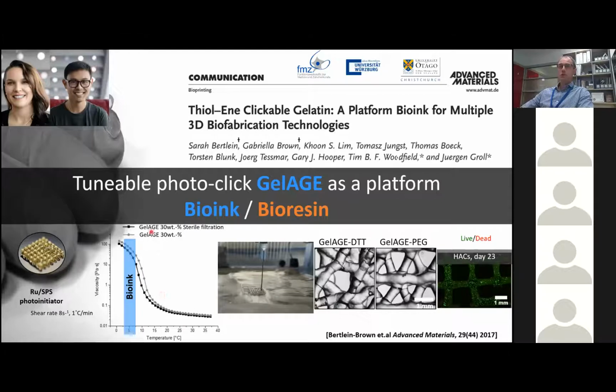So what we're able to do is work with a family of different types of GelAGE materials, and what we were discovering when we did quite an extensive range of rheological characterization, and this was done with Jürgen Groll's group at the University of Würzburg, is that at low temperatures we had a really nice viscosity profile which made it ideal for extrusion-based bioprinting in the presence then of a range of different types of cross-linkers, including DTT or PEG. And when we included cells, we saw really nice cell viability. So again, that's using the same photoinitiator system, and we could now have a GelAGE bioink.